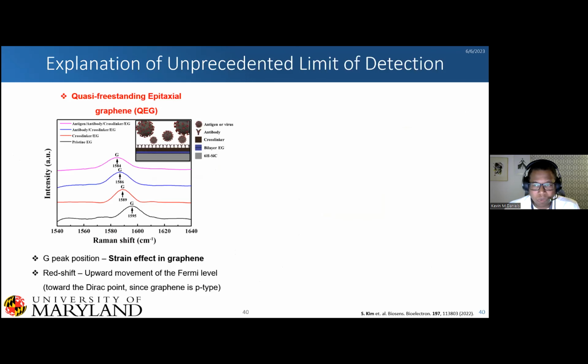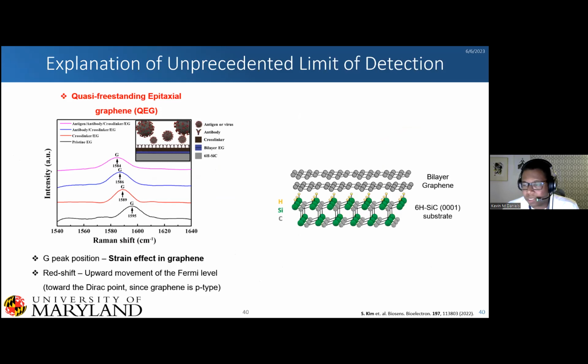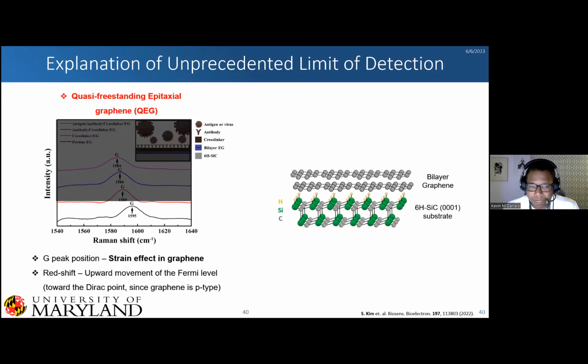And so, what's the explanation of this really unprecedented limit of detection? Because if we're talking about 4 bindings, we're only talking about 4 electrons being generated, which would not cause our device's conductivity to change 30%. So what is happening? And so this is our structure here. We have our silicon carbide, silicon bonds are passivated with hydrogen, and we have our bilayer graphene on top.